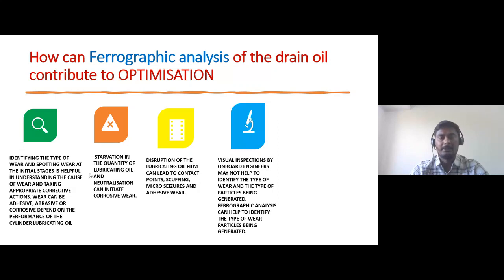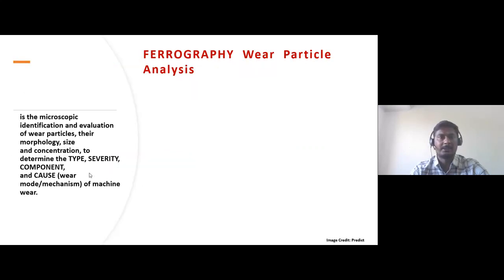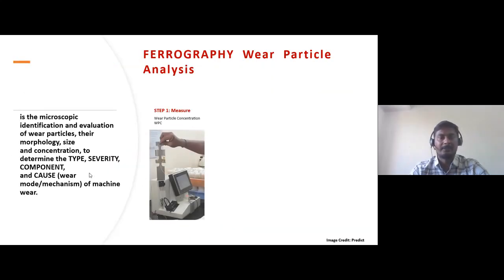It's a good thing. Whenever you do ferrography, you can understand the structure inside the liners, and when wear occurs you can understand that too. Accumulation of particles, some particles and also abrasive wear like third body abrasion and cutting wear, you can also understand. So this is the ferrography analysis.